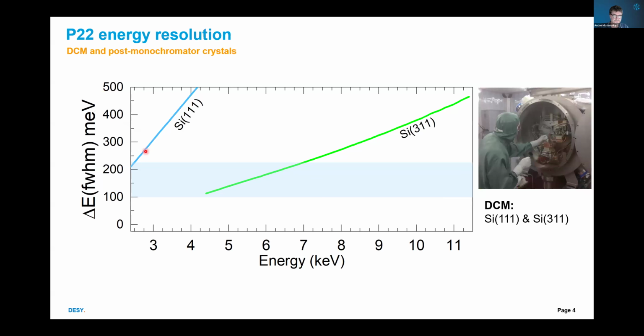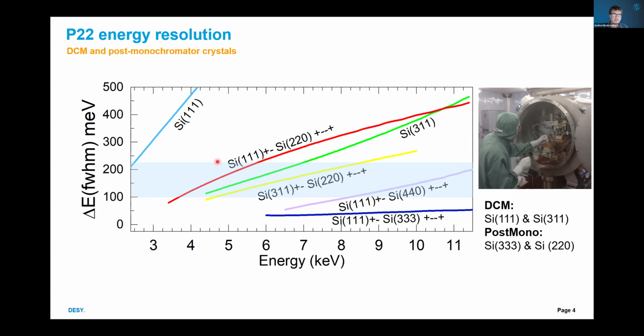So here are the energy characteristics of our 2 crystal pairs. In the double crystal monochromator, we start at 2.4 kilo electron volts, which is the minimum for crystal optics, and we cover the range up to 12 kilo electron volts. And as I said, if you need better energy resolution, we have an additional post-monochromator, and at every excitation energy we can offer an energy resolution that is well sufficient for solid-state spectroscopies, which is better than 200 millielectron volts.